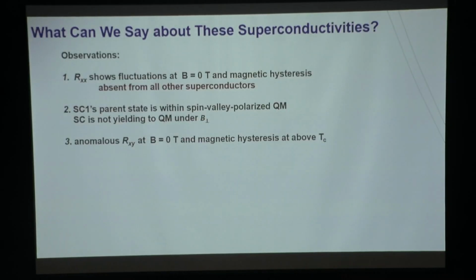So let me summarize what I've shown you in this superconductor part. Phenomenologically, we got Rxx fluctuation and hysteresis in the superconducting state, and this is absent from all other superconductors. And even above Tc, it has anomalous Rxy and hysteresis. This is again absent from all other superconductors.